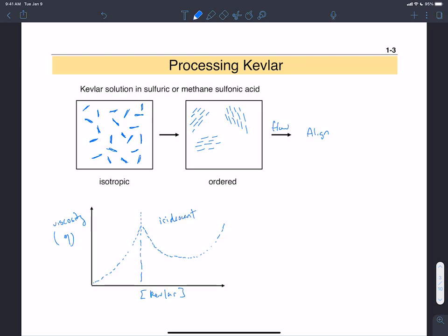And this has to do with how the anisotropic behavior of light can interact with these domains, where you can have diffraction of the light in different ways. So you get these sort of rainbow effects or swirly looking, milky, cloudy substances in your solution. And actually, as we mentioned last time at the discovery of Kevlar, they initially had these sort of milky suspensions developed that they thought wouldn't really be good for anything. And then just to see what happened, they tried to make fibers, and these fibers ended up being higher strength and better mechanical properties than really anything else that they had at the time.